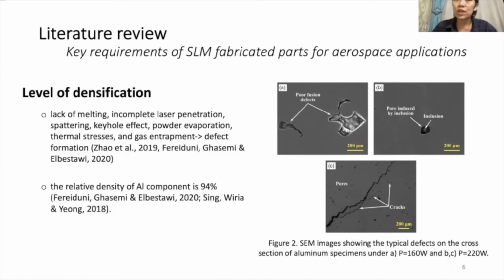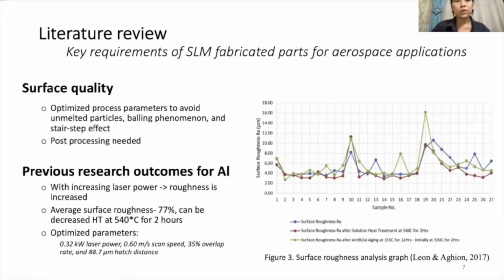But however, there are sufficient studies optimizing process parameters and utilizing different post-processing techniques that help to solve the density problems of selective laser parts by eliminating defect formation. So the next slide will concern surface quality. Surface roughness is known as one of the limitations of selective laser melting technology caused by layer nature. Especially in components with complex geometry, surface quality is low due to the difficulty to machine. Partially melted powder particles or even unmelted particles, balling phenomenon, and stair-step effect are the most frequent factors defining the surface quality of the printed component.